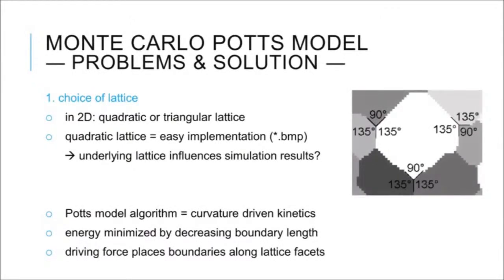The result can be seen here. You see that the boundaries are very straight, not to say they are more or less linear. And you see that apparently we have very peculiar angles. At each triple junction, at each triple point, we have one angle that is 90 degrees and two further angles that are 135 degrees. This is just wrong, because I've mentioned before that when all our boundaries have the same energies, the angles at such triple junctions should be 120 degrees each. And of course, this is apparently not the case.